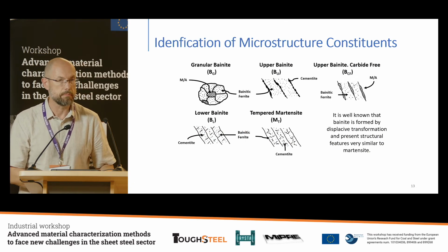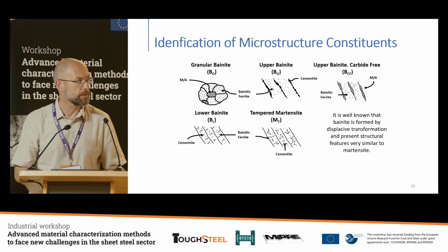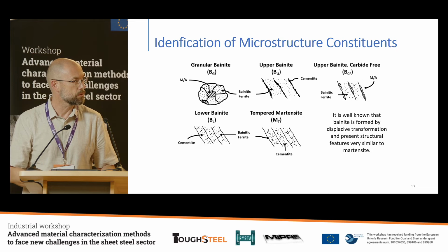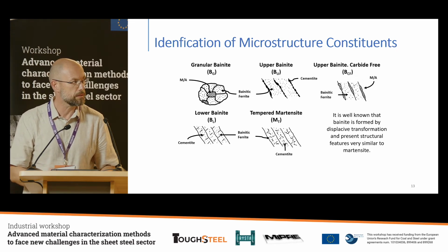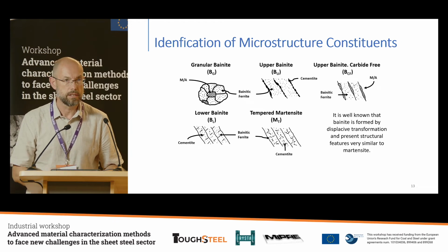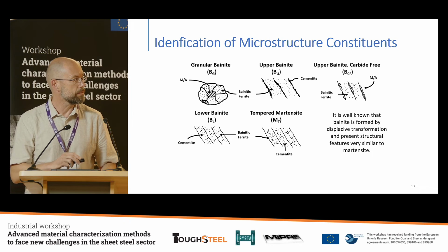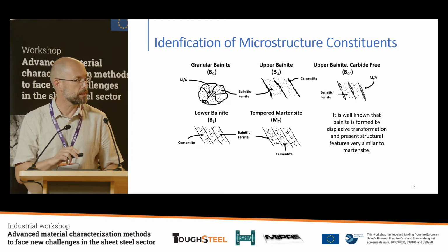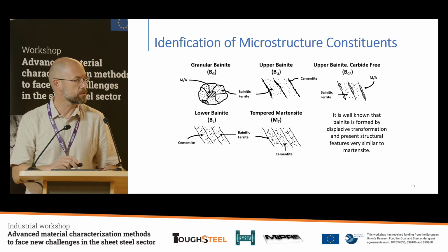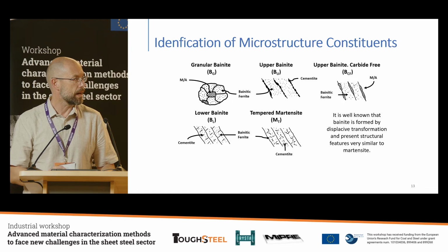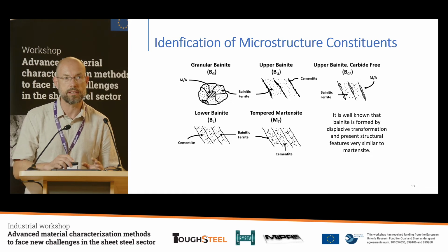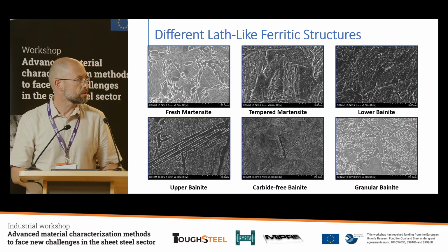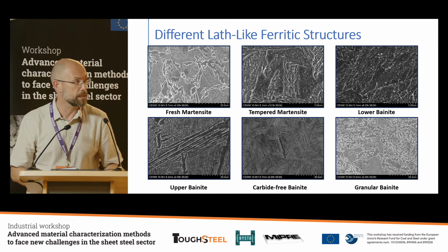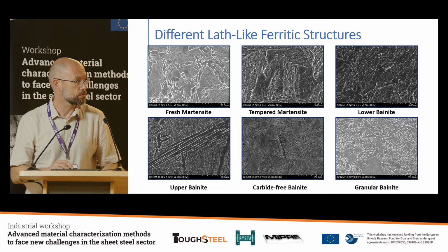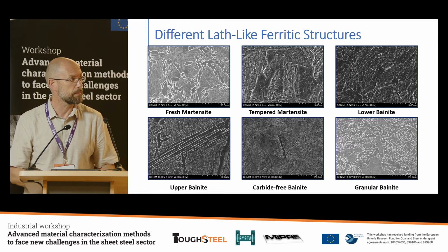With these mechanical results in mind, let me give you a rapid guide of the different types of microstructures that we are going to face. In these graphics, when we say bainite, it is something quite broad because there are different types of bainites here, and they behave in completely different ways. We call it granular bainite when you have this shape. Upper bainite has carbides here and ferritic laths over there. When there are no carbides but there is retained austenite, it is called a carbide-free bainitic microstructure. And lower bainite is when the precipitates are inside the ferrite. When you have tempered martensite, you also have precipitates inside the ferrite, but they don't have a preferential orientation. So these are the microstructures that you can obtain during the press hardening process, and you can see the difference between the ones that I mentioned before.